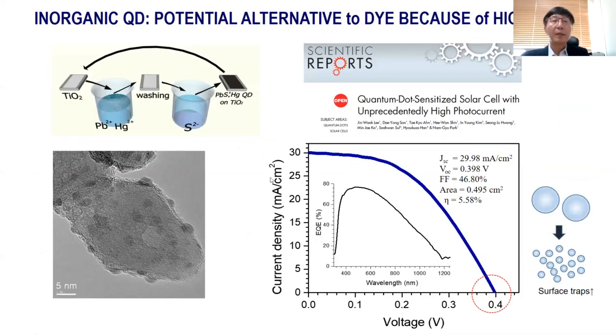Therefore, people would like to replace the organic sensitizer to increase the efficiency further. The inorganic quantum dot is a potential candidate because it has a very high absorption coefficient. For instance, lead sulfide has a very narrow band gap of about 0.5 eV. However, if you decrease the size, you undergo the quantum size effect, and the band gap increases to about 1.1 eV, which is suitable for a photovoltaic material.